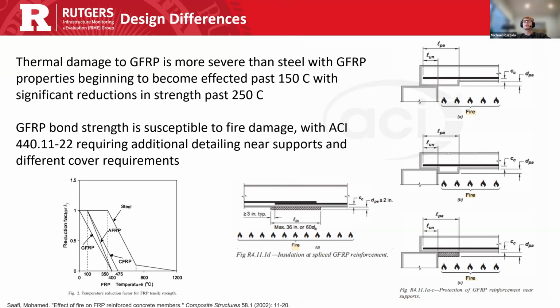So there are some additional design requirements: adjusting the clear cover, or adding insulation to critical areas, mainly against the embankment or the abutment that it's resting on, or critical sections like splices. The reason those sections need to be protected is because bond strength is susceptible to fire damage. It undergoes a fairly significant reduction. So additional detailing is used to compensate for that and give additional time to resist that damage.